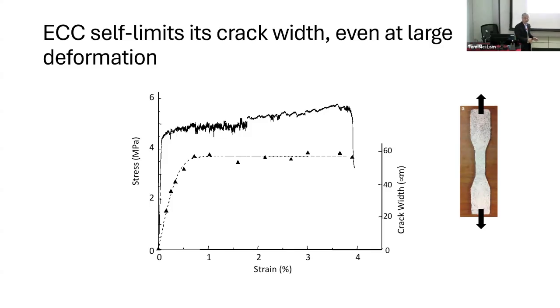And this is done by itself. We are not using any steel reinforcement. This is an intrinsic property of ECC. ECC has the intrinsic behavior of having tight crack width, even though you deform it to a very large extent. Okay. Now that is very important, and I emphasize that because it's critical to durability of infrastructures. You see that durability, or conversely, the degradation of infrastructure is strongly related to the width of cracks in the structure under surface.